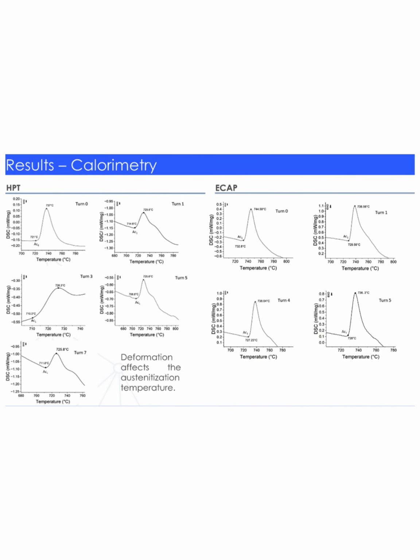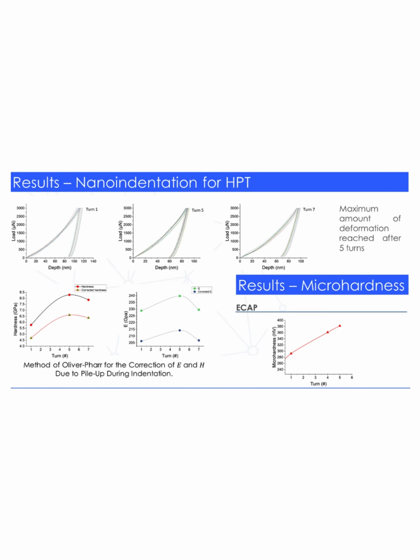The distribution of phases changed with the constant accumulation of deformation after each ECAP pass and the direction of the process flow. DSC results show that in both ECAP and HPT, the austenitic transformation is affected by the deformation introduced in the samples, decreasing both the AC1 and the maximum transformation peak temperature as the number of passes increases. Nano-indentation results indicate that both hardness and elastic modulus increase from turn 1 to 5. However, from turn 5 to 7, a decrease is observed in both cases.